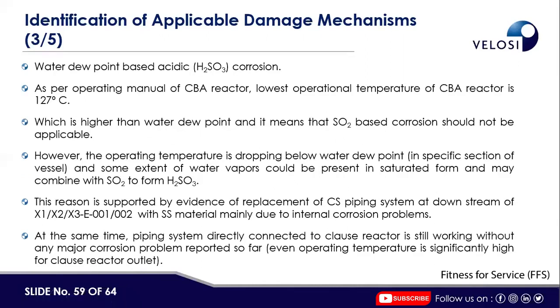Water dew point based SO2/H2SO3 corrosion. As per the operating manual of the CBA reactor, the lowest operating temperature of the reactor is 127 degrees Celsius, which is higher than the water dew point, and it means that SO2 based corrosion should not be applicable. However, the operating temperature is dropping below the water dew point in specific sections of the vessel, and some extent of water vapors could be present in saturated form and may combine with SO2 to form H2SO3, and that was the major issue in our opinion.